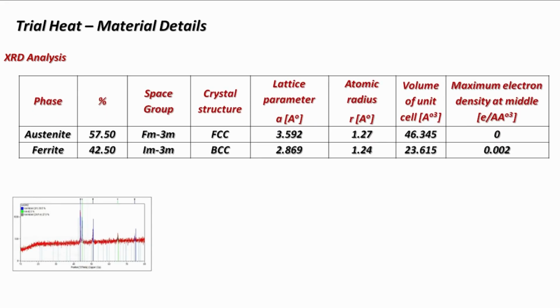Further, this solution annealed material was subjected to XRD analysis to understand the basic characteristics of the material, and we can see austenite is around 57.5% and ferrite is around 42.5%. The crystal structure is clearly displayed: austenite has a face-centered cubic system and ferrite has a body-centered cubic system.